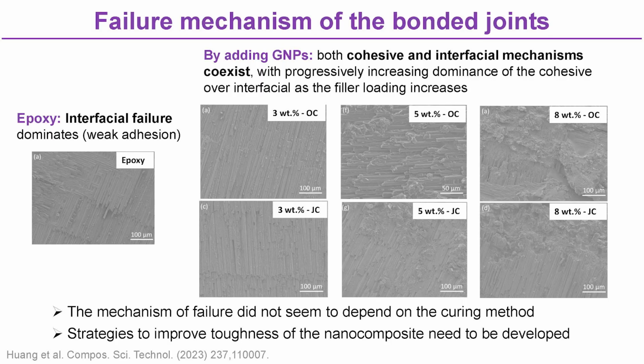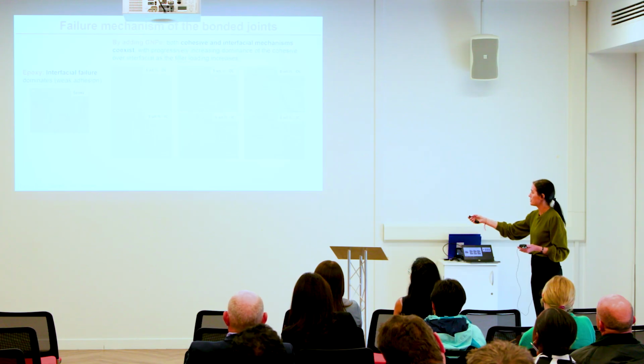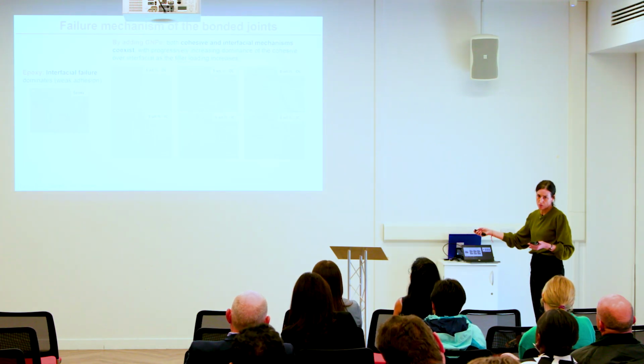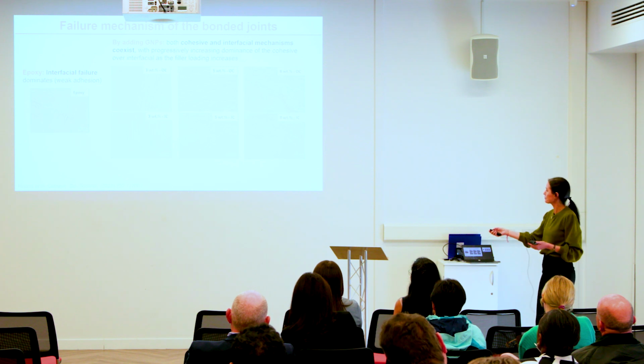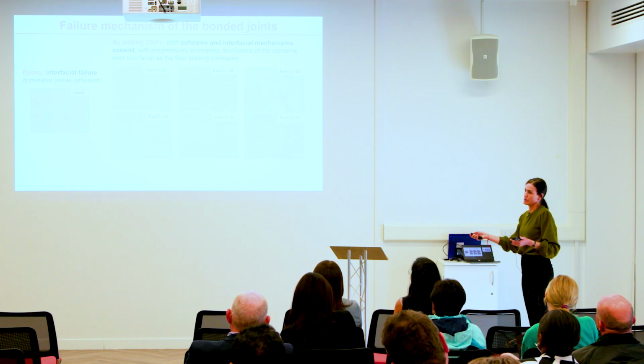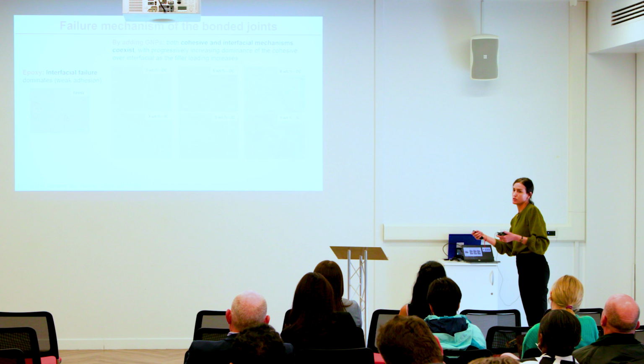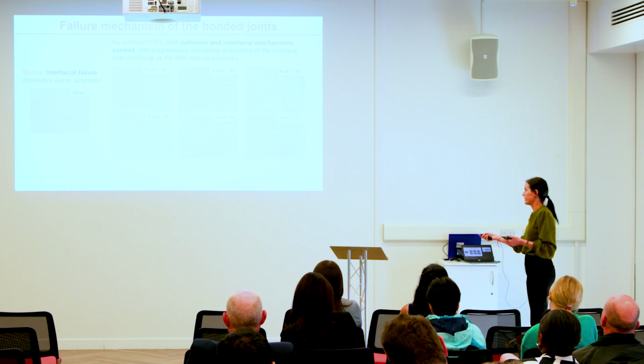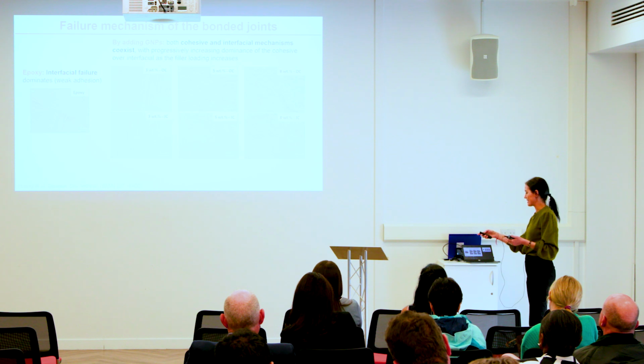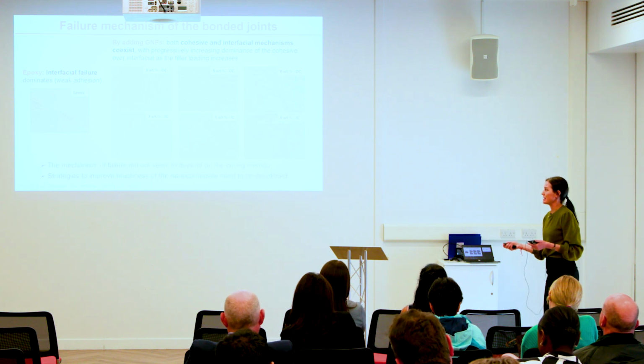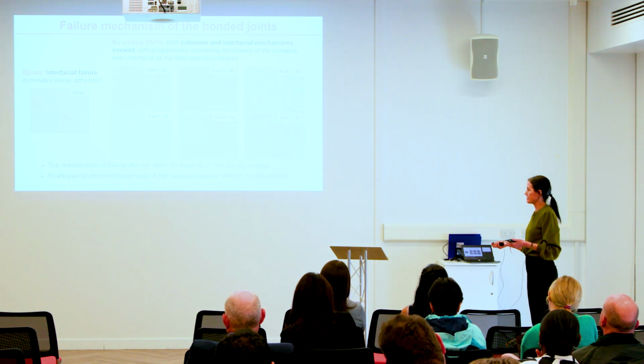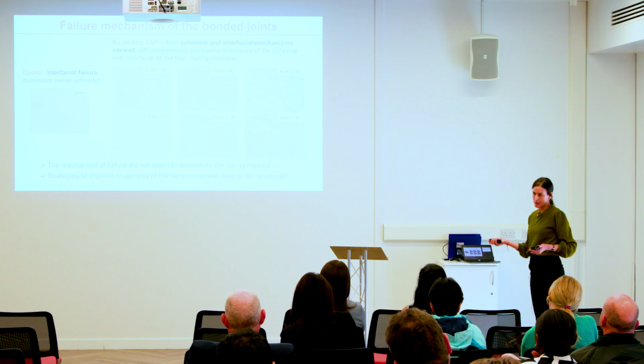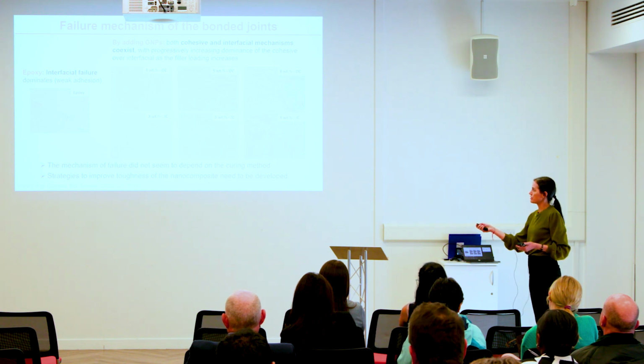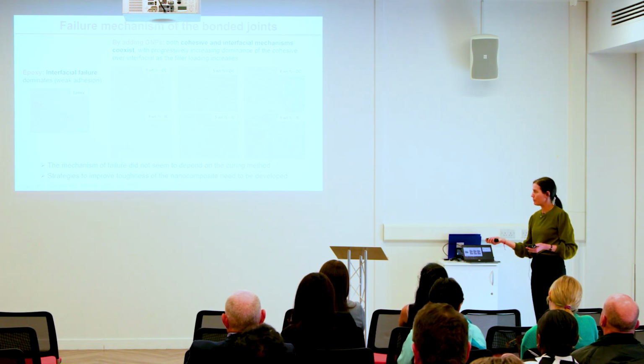Indeed, we see that as we go from 3% to 5% to 8%, we see more and more regions covered by this residue from the adhesive, which suggests that we are actually creating increasingly stronger interfaces as we are adding more and more graphene to our adhesive. In any case, the mechanism of failure did not seem to depend on the curing method. We see very similar results for the oven-cured samples and for the Joule-cured samples.